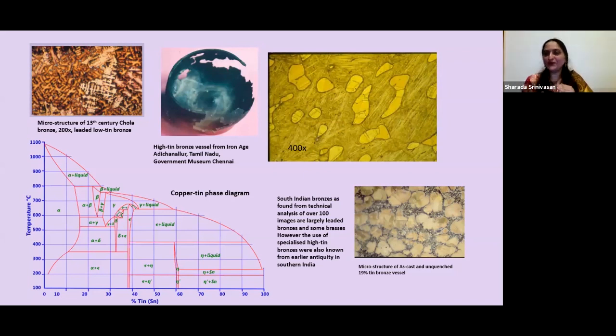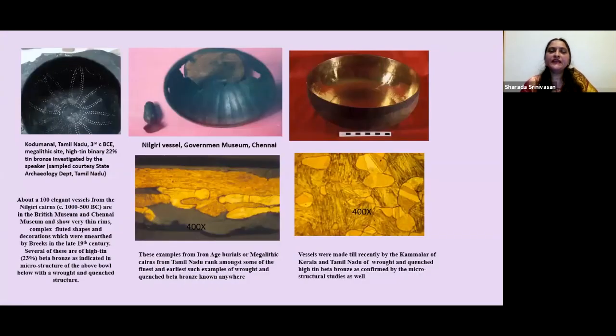But there is also another story: the mirrors in Kerala, which I'm going to talk about, actually optimize the presence of this embrittling delta phase because it has very good specular properties and a very good mirror finish. And those mirrors had about 33% tin content, where this delta phase is optimized. So as I was mentioning, these are some examples of this very remarkable material, these high tin beta bronzes, as we call them. And you see such vessels from the Nilgiris, and you're looking at the microstructure that I was talking about, again the needle-like beta phase and the islands of alpha plus beta phase, and again extraordinarily thin rims.